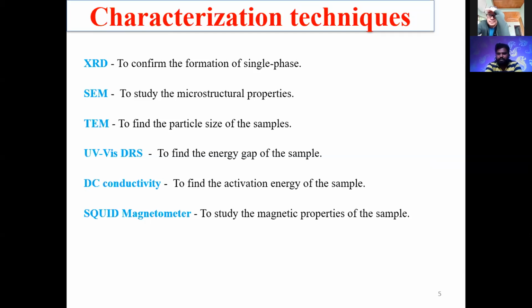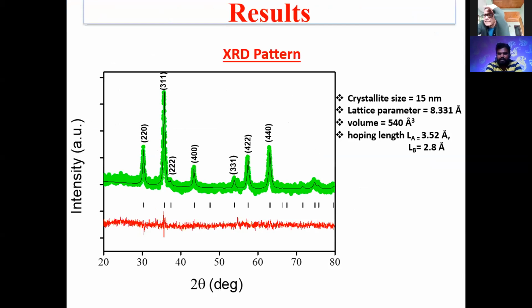Results and discussion. This is the XRD pattern. It was fitted by Rietveld refinement software. It confirms the single phase formation, and the indexed HKL values confirm the spinel cubic structure of the samples. From this XRD pattern, we have calculated the crystallite size, found to be 15 nanometers. The lattice parameter is found to be 8.331 angstrom. Volume and hopping length have also been calculated from the XRD pattern.